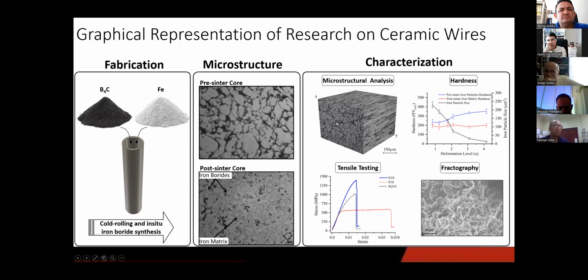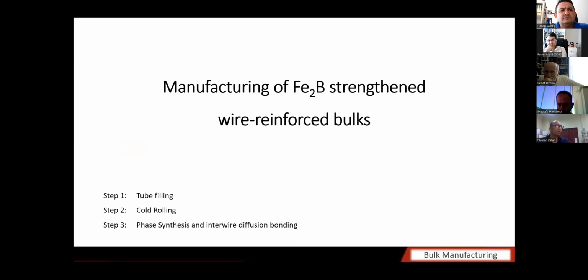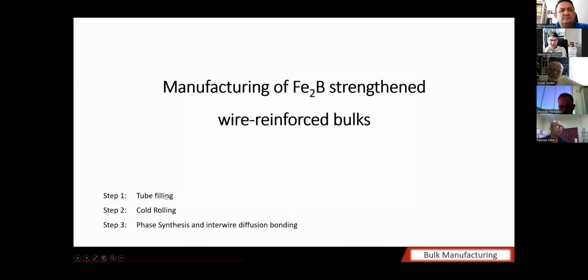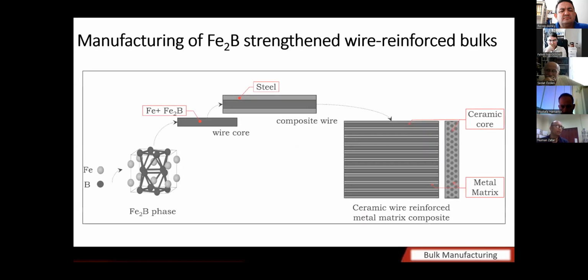Microstructural analysis. This region is transverse to cold rolling. This is parallel to the cold rolling. Influence of all these deformations on the hardness, tensile testing, and fractography. The next is manufacturing of wire reinforced bulks. Again, very simple: tube filling, cold rolling, and phase synthesis and interwire diffusion bonding. 3 steps, not too complicated.